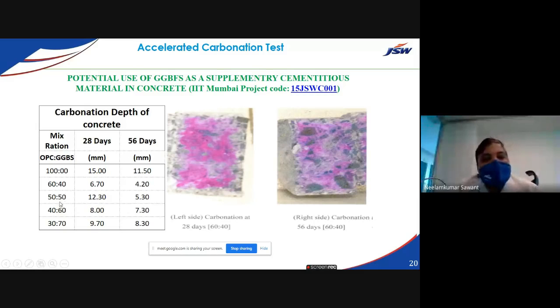And if I am using 50% replacement of OPC with GGBS, after 28 days the carbonation depth is about 12 mm. After 56 days, when the concrete is contracting, the pores are filling up and the concrete is gaining strength with the help of the secondary reaction of GGBS, the carbonation depth observed is about 5 mm. So we can see from these studies, whenever the ratio is about 60-40 or 50-50, GGBS plays an important role in resisting carbonation depth. So this is another advantage from the durability point of view.